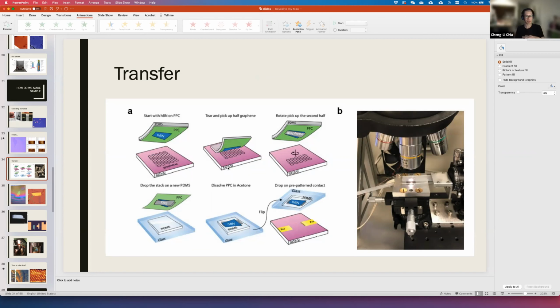But for transport experiments, they don't need to put a tip on top of the sample. So when they are making a sample, they can pick up graphene, tear it, and then pick up another hBN. Basically you can protect your graphene between two hBN, and then it will become very clean because it will never touch the PDMS or the polymer you are using. It only touches silicon oxide. And silicon oxide is usually very clean.